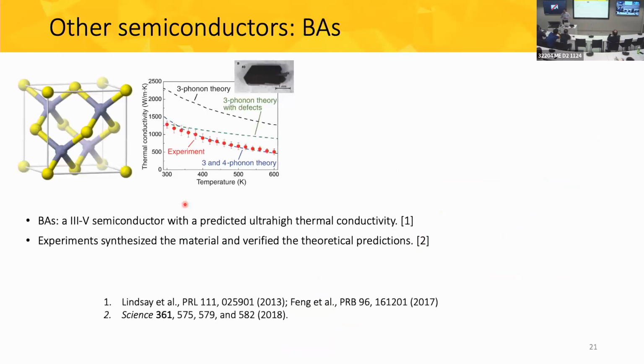Another important semiconductor with an indirect band gap is boron arsenide. And I want to mention this because boron arsenide is one of the largest successes of theory in recent years. So boron arsenide was predicted from theory to have an ultra high thermal conductivity that was second only to diamond. It was a very bold prediction that was subsequently verified experimentally. There were 3 Science papers in the summer of 2018 that verified that indeed the boron arsenide has a record high thermal conductivity with only diamond surpassing it.